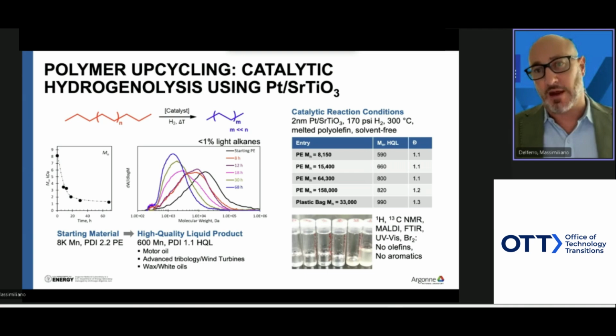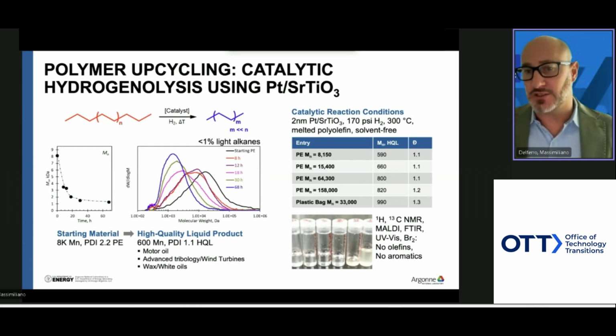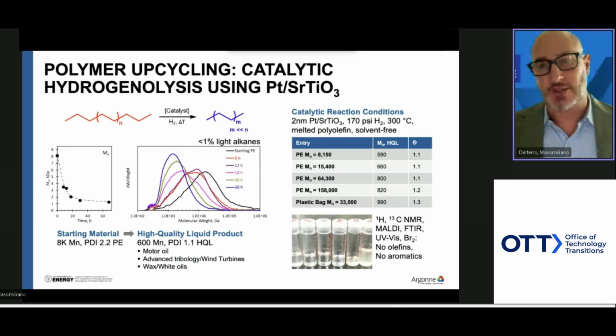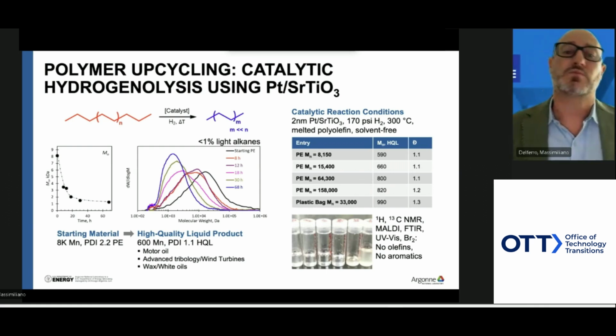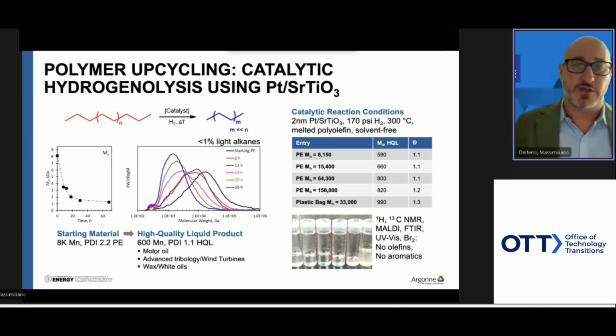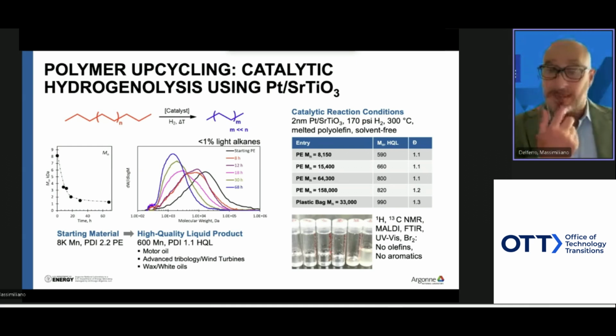What we learned in the past few years is that the reaction is independent of the structure and the molecular weight of the product, but what matters is the catalyst per se. And the polydispersity is a very interesting characteristic of this reaction. In fact, we go from a large polydispersity that was initially present in the polyolefin waste to a very narrow distribution. The liquids are very interesting. There are no olefins, no aromatics, are pure alkanes. And they have a very particular application, for example, and I will show you later, as lubricating and tribological oils.